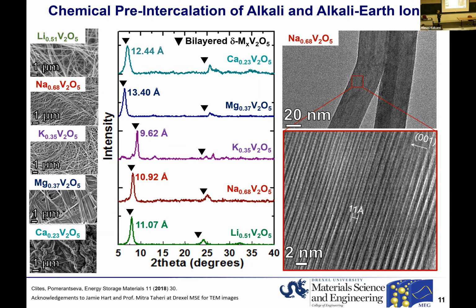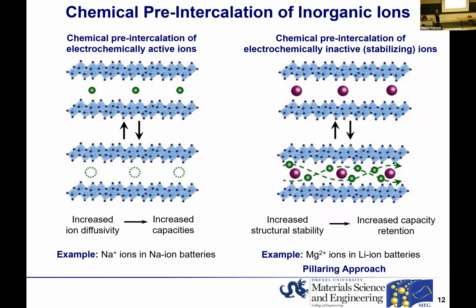We noticed that the interlayer distance in the products really depends on the nature of the chemically pre-intercalated ion. Moreover, we realized that the interlayer distance increases with the increase of the hydrated ion radius. And that implies that the ions are being pre-intercalated not in their simply ionic form, but in their hydrated form. The chemical pre-intercalation of ions is accompanied by pre-intercalation of water molecules. And this ability to make these materials, from the point of view of energy storage, allows us to investigate two distinct directions.